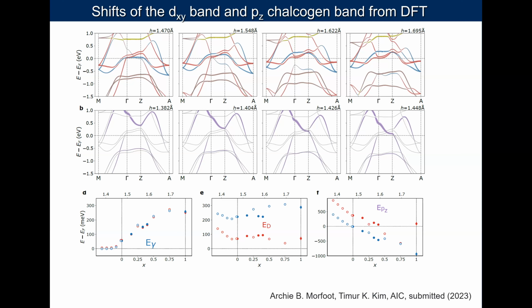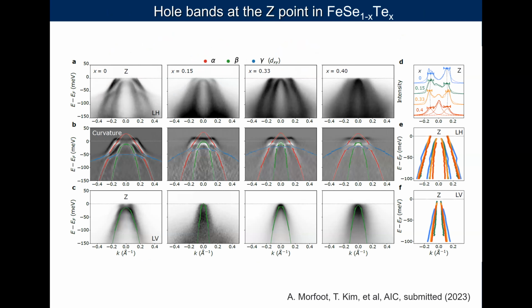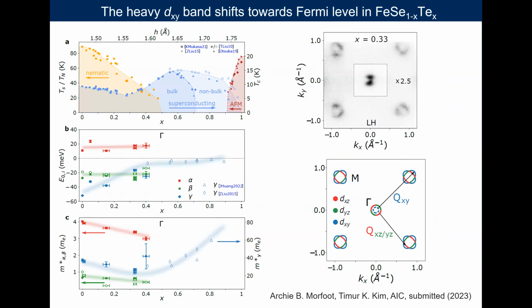And is it possible to bring up the other band and suppress the dxy you had originally at the Dirac point? I mean, as you see experimentally, it's the first time we see the dxy band nicely shifting away. We always thought that it was quite immune, but it seems like it's very sensitive to tellurium substitution. So I think now we have a cocktail of lots of bands, low energy interactions, and a pz band happening as you are on top of the dome. So I think it's quite a rich environment for physics at that particular point.